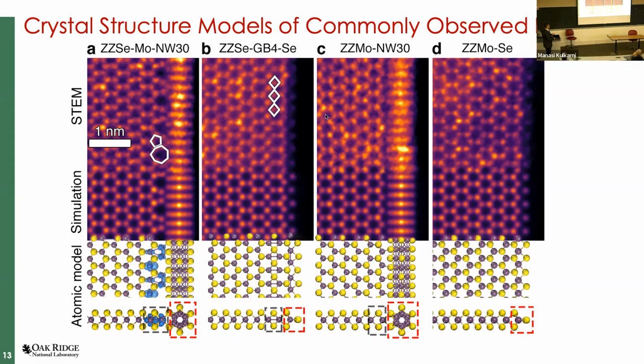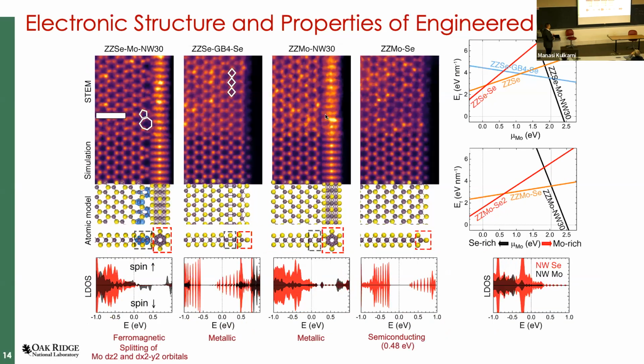So this is good. Experiments on top, simulations, they match pretty well. From that, we were able to extract the atomic structure model. And then now let's use theory again to understand what new functional properties we have. So these are the 4 commonly reconstructed edges. Again, STEM, multi-slice simulations, the atomic structure model, and then you can calculate what the density of states are for these materials. Pretty interesting. If you take, for example, the point right here, this is your molybdenum.